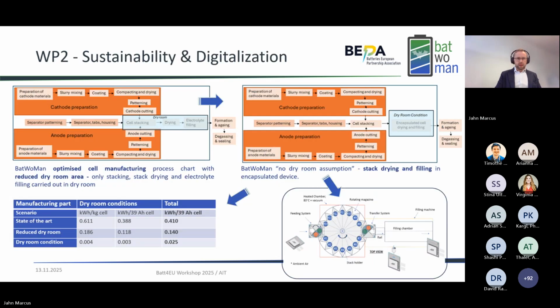So first of all, work package 2, sustainability and digitalization. What we tried to do here was to go for an improved dry room design, or basically look at what the improved dry room design could actually do for us. In the first scenario, we tried to reduce the dry room need just for cell stacking, drying and electrolyte filling, so it's closer to the conventional process. The final scenario was then to reduce the dry room condition only for the finished stacked cell and the electrolyte filling itself.